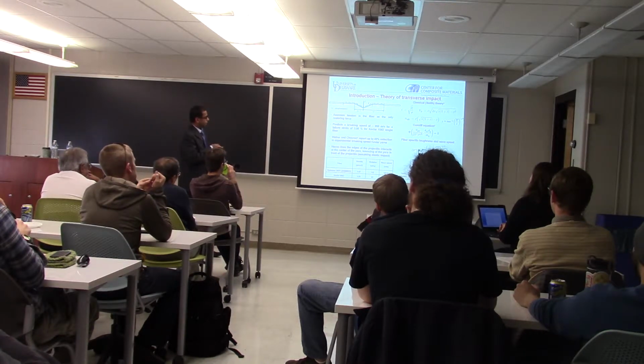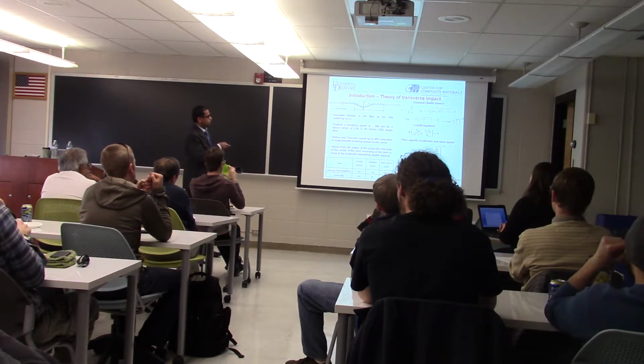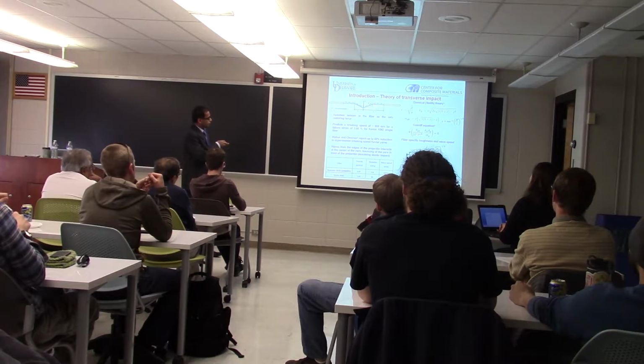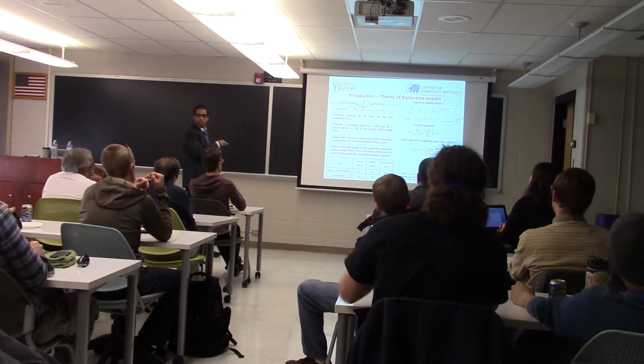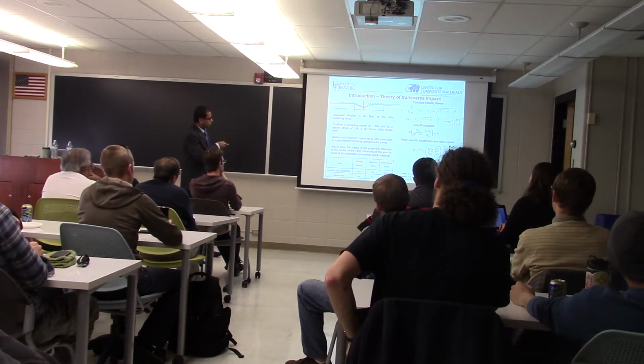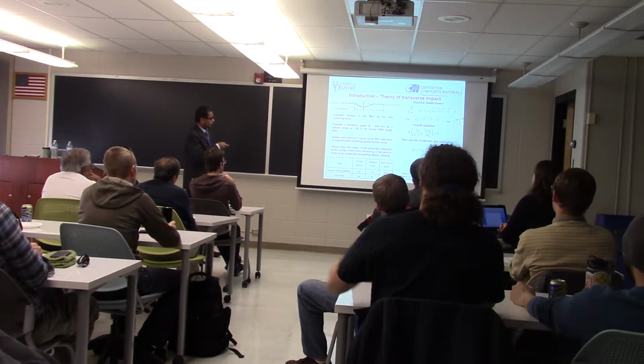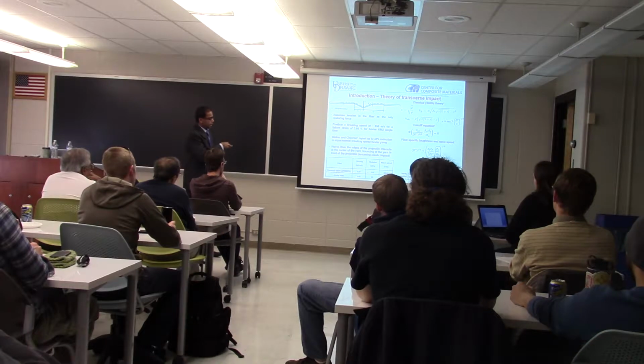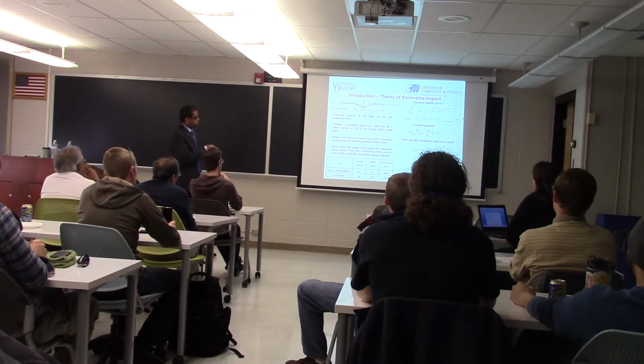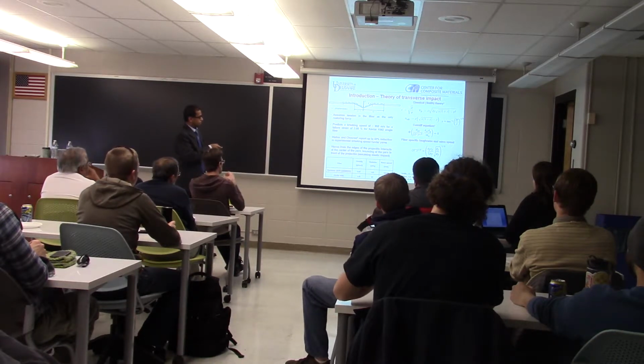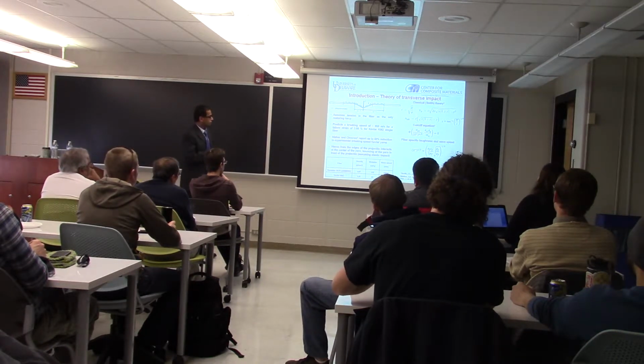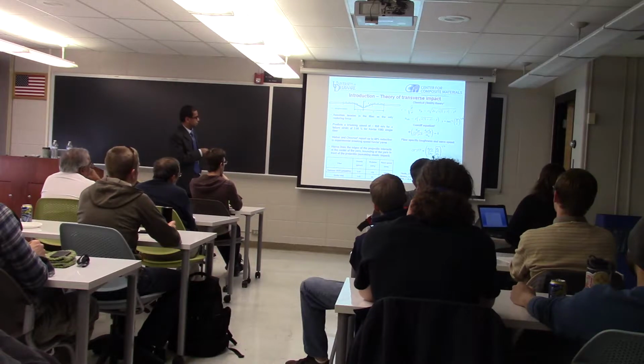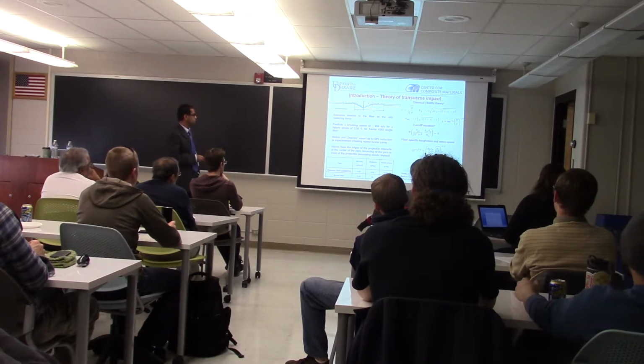So the longitudinal wave strains the fiber and causes the material to flow inward towards the impact location. And when the transverse wave is much slower than the longitudinal wave, and when the transverse wave arrives, the material moves in the direction of the impact. So one can determine the longitudinal wave speed using this equation, which is a material property, whereas the transverse wave speed is dependent on the strain in the material and also the wave speed itself.